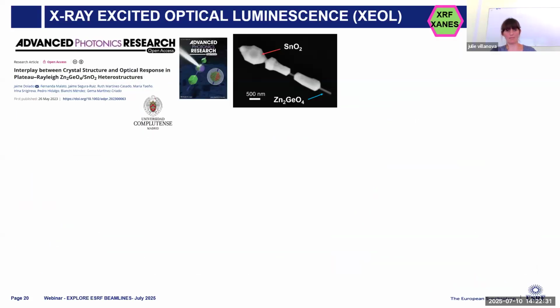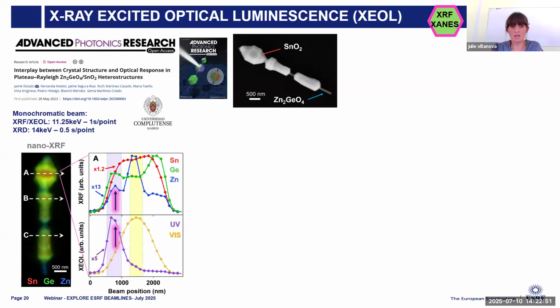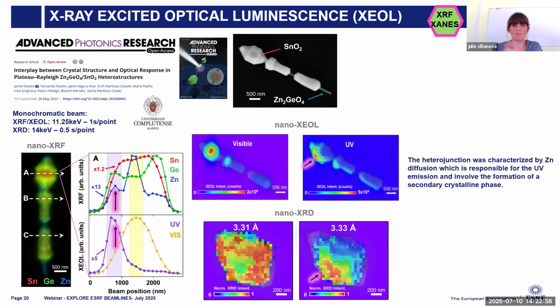The example that I chose to illustrate the technique is a study about a heterostructure that is illustrated here. This is a SEM image of the heterostructure that I will talk about. You have a core of zinc germanium oxide with a heterostructure of tin oxide around. Those systems have been scanned by X-ray fluorescence and, at the same time, by XEOL. What we see when we plot the profile here is, first, a zinc diffusion in the heterostructure, and that the zinc diffusion is responsible for the UV emission that we see here on the XEOL map.